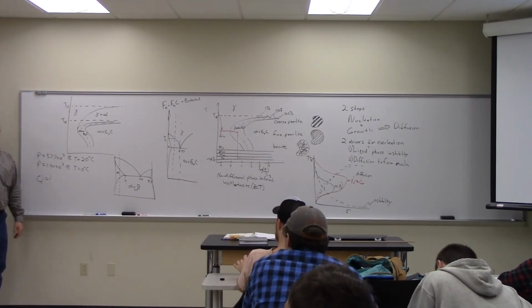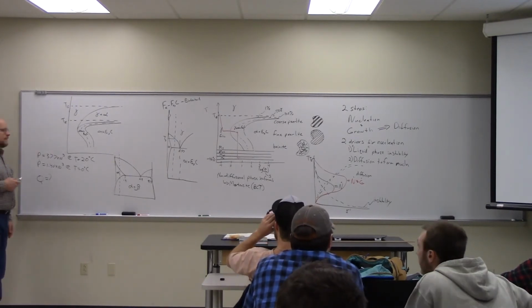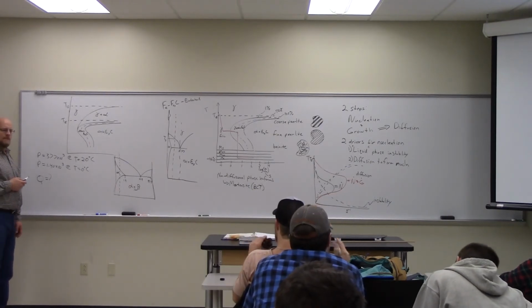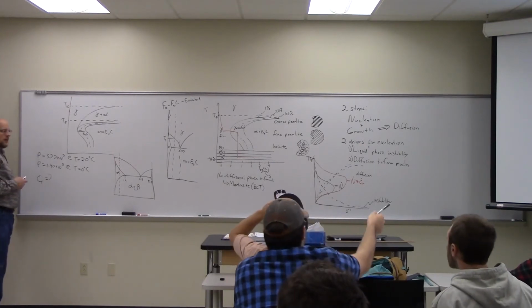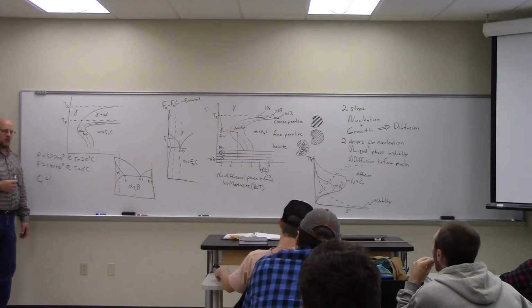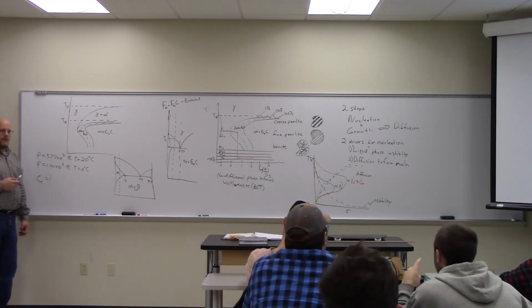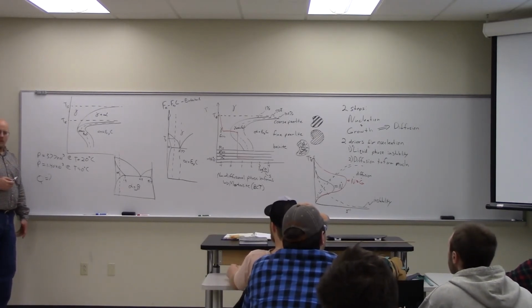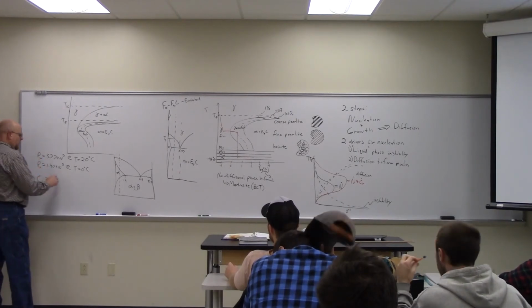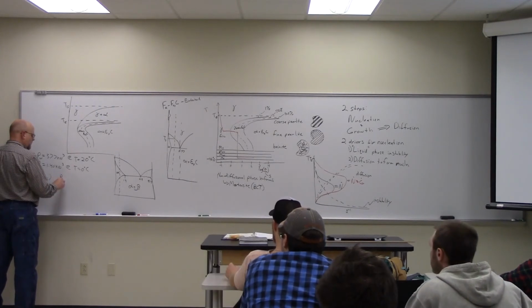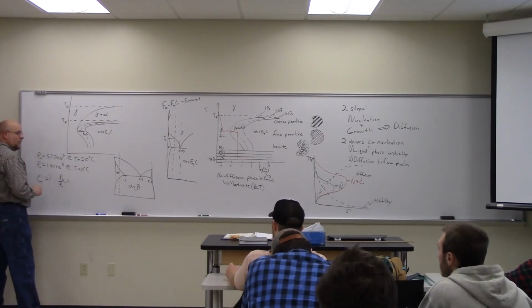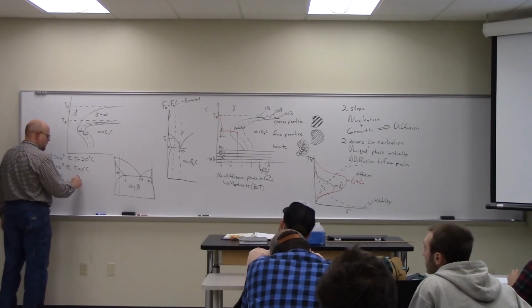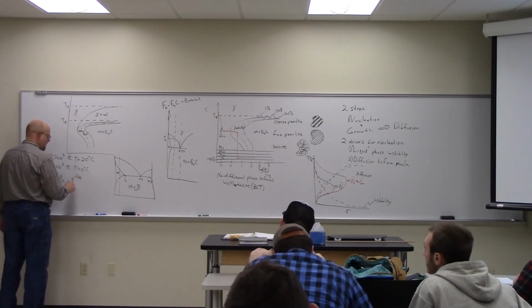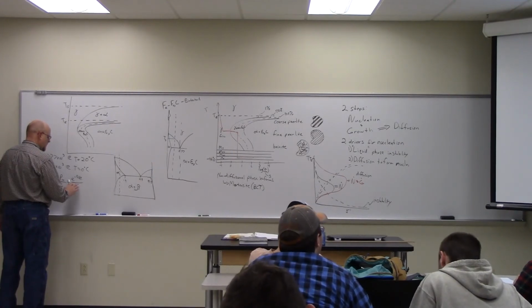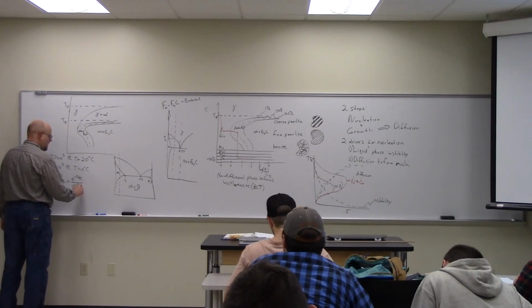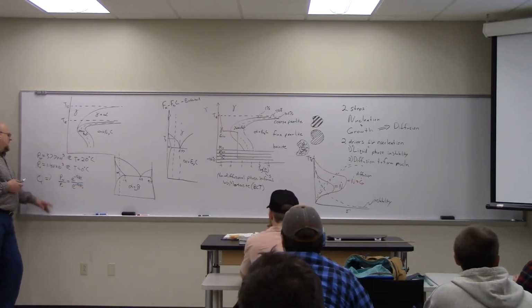So how would I solve for Q? Divide the whole thing by C. Just a reminder, we've done this once before with diffusion. We want to solve for Q. What do we do? Take a ratio. Remember, we have P20 and P0. So what we really want is the ratio of P20 divided by P0 so that the C's cancel out. And that's going to be e to the minus Q over RT20, which is R times 293, divided by e to the minus Q over RT0. P dot is the precipitation rate.